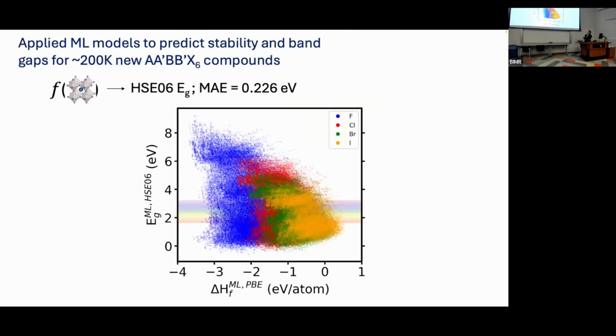And that gives us a set of structures that we can then use as input to train another model in order to predict the band gap energy. In this case, we use a much more rigorous functional than PBE. So PBE is okay for solid state materials, typically for the ground state and for the stability, but it's not sufficient for band gap. The PBE functional has about 2 eV error for band gaps. So if you want to produce a database that might be useful for experimentalists to pursue potential photovoltaic materials, then you want to make sure you have the right estimates for stability and also the right estimates for band gaps. So in this case, we use the HSE06 functional, which has a more accurate band gap, and we train a model that takes these MLIP structures and produces the band gap, and we subsequently validated the model to have an error of about 0.2 eV relative to HSE06. So we can produce a plot like this, which gives us stable materials from this large space, but also the band gaps within a certain range.